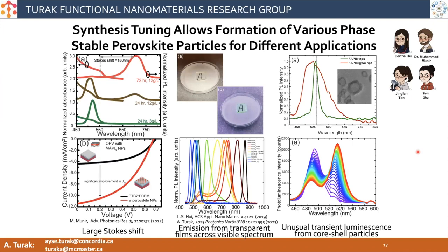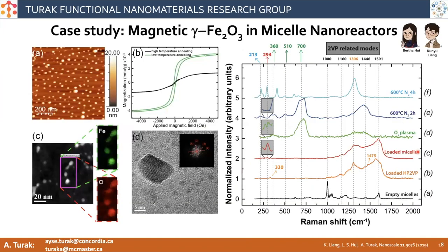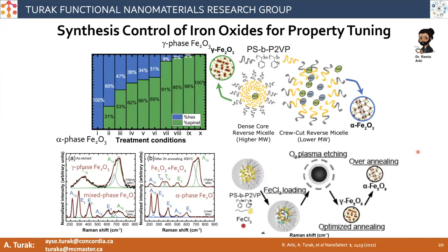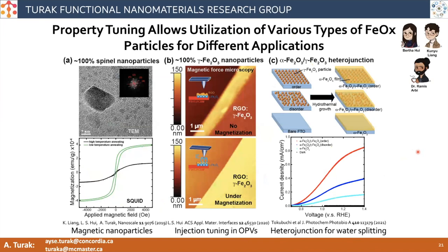But basically, we can also use this kind of thing to learn about magnetic iron oxide nanoparticles, for example, which we've been working on for a number of years. I'm just going to skip to what we can do with that. So it allows us to, again, tune the properties, tune the structure, to be able to change the phase without changing the size, change the order, for example, without affecting either the size or the phase, which can lead to interesting results, including the magnetic properties, increasing the ability to do water splitting, these sorts of things.